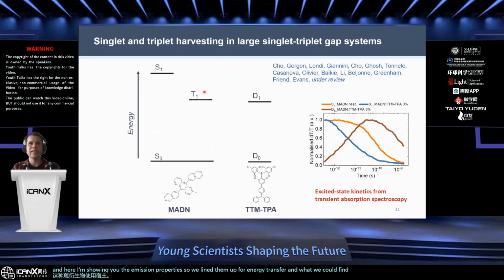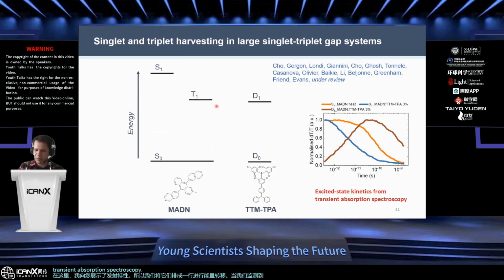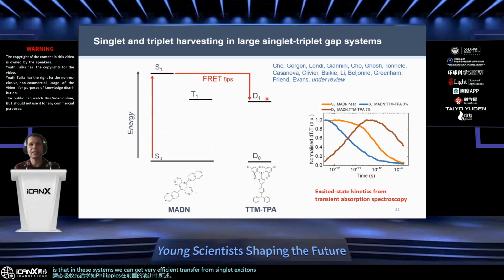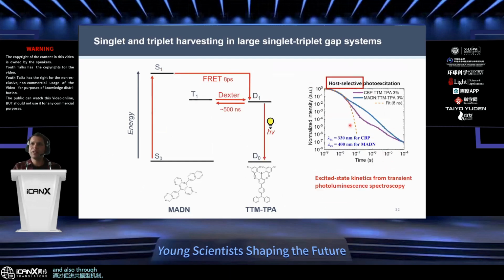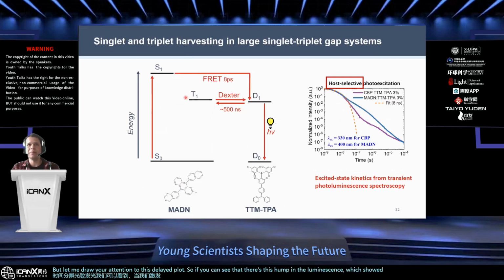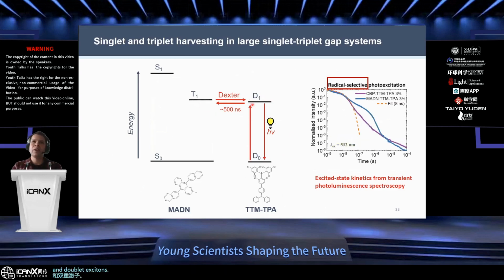And what we could find when we monitored the transient absorption spectroscopy, as Philip described in the previous talk, is that in these systems, we can get very efficient transfer from singlet excitons to doublet excitons through a Forster resonance type mechanism. And also through monitoring the time resolved photoluminescence, we could see that we set up efficient radical luminescence when we excite the MADN. But let me draw your attention to this delayed plot. You can see that there's this hump in the luminescence, which shows that there's a delayed emission as the system sets up an equilibrium between triplet and doublet excitons. And this happens whether or not you excite directly from the host, or in this case, also through the radicals.